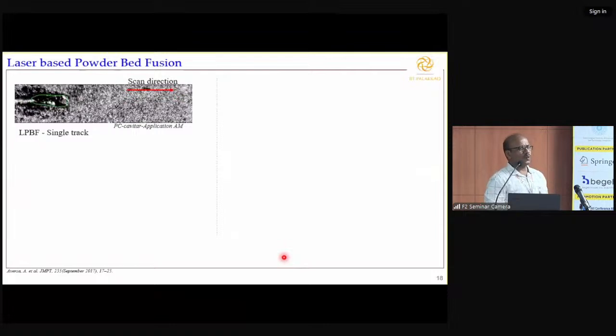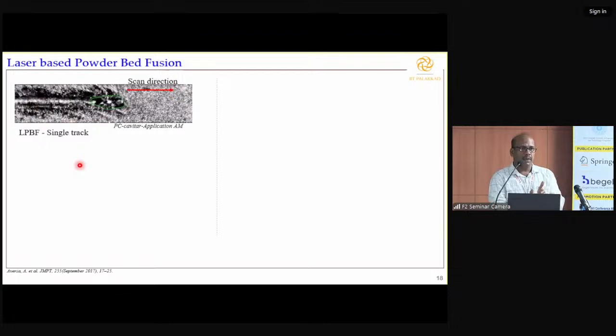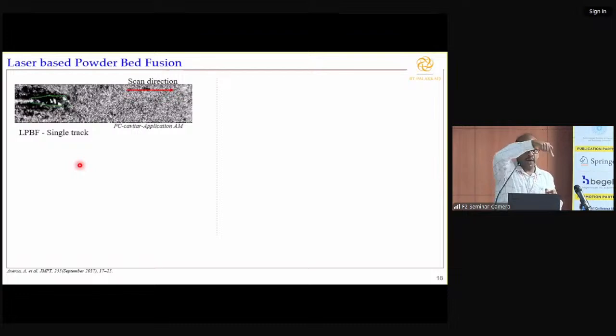Now, when I want to work on this single layer, how are things? This is the image captured while doing the process. If you see here, there's powder spread on the platform, then the laser source goes from left to right. Then this green colored line, which is encircled over there, is a melt pool. The melt pool also slowly moves because the laser you're using is a high power laser source, and it moves like this on the powder. What happens is that it melts the powder and then slowly moves. Whenever it is moving, it is dragging that molten metal also.